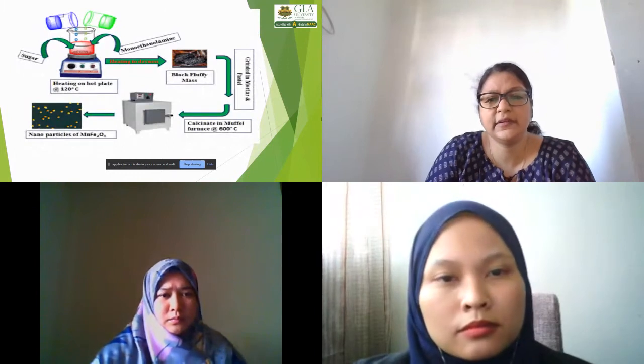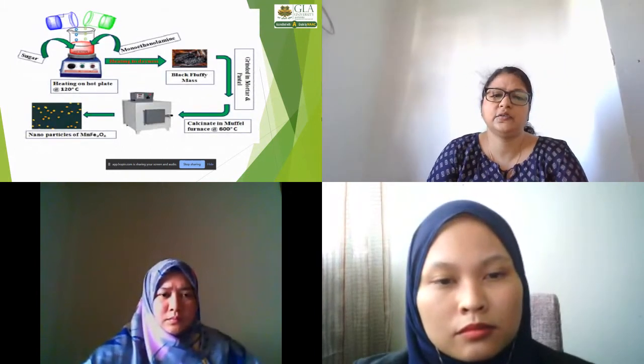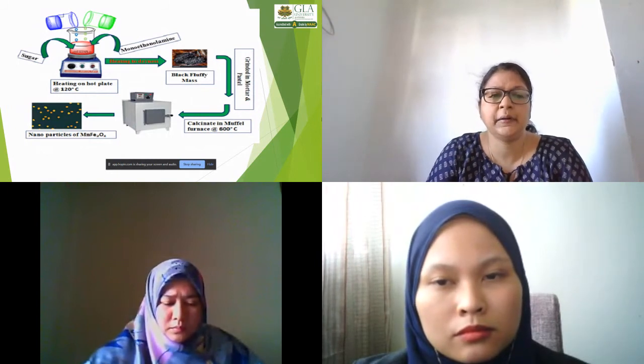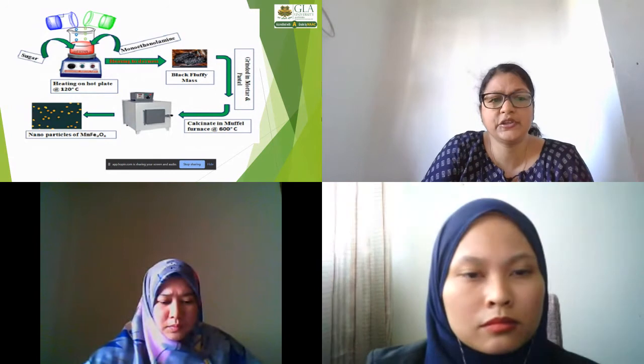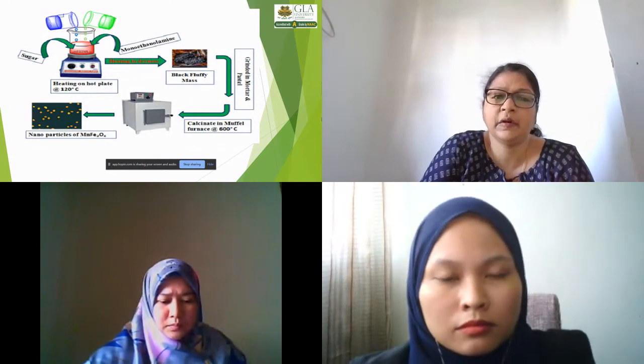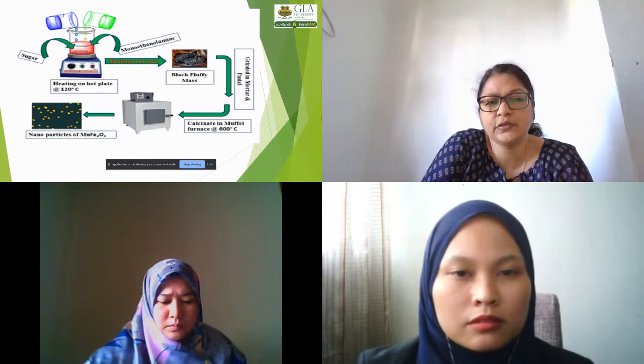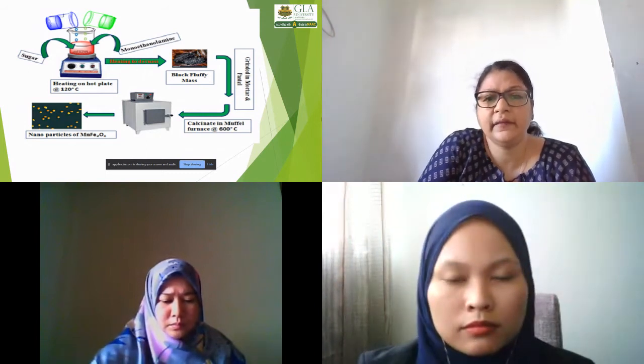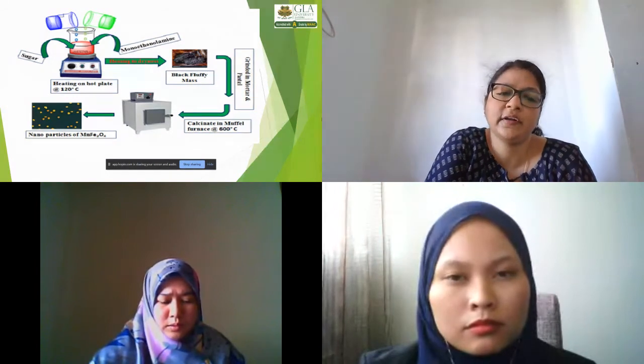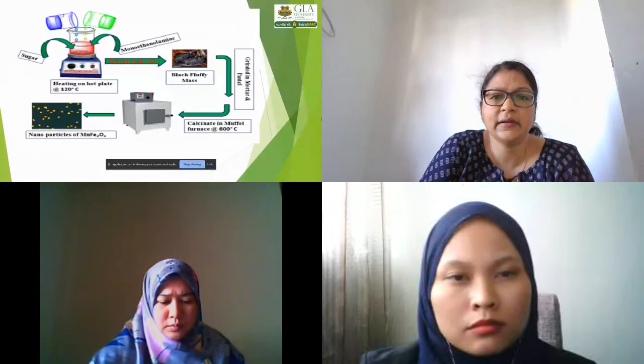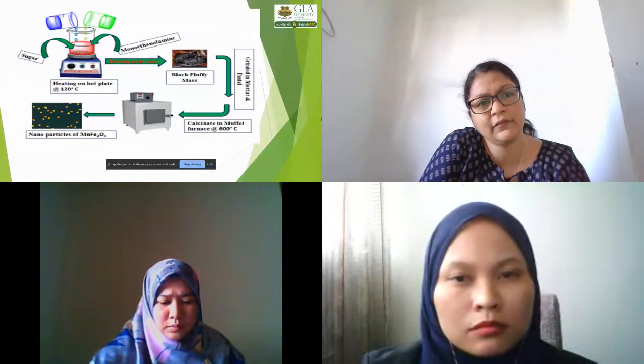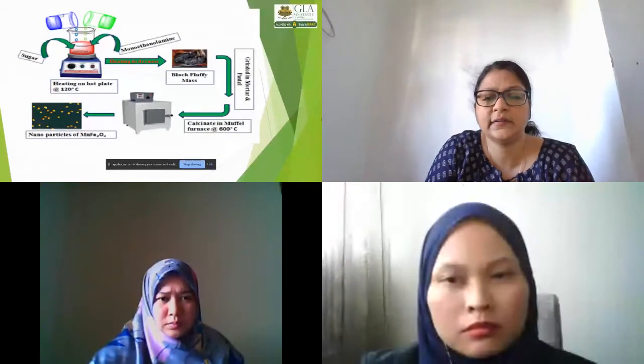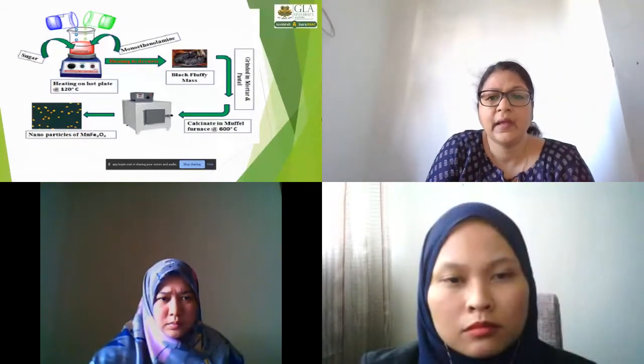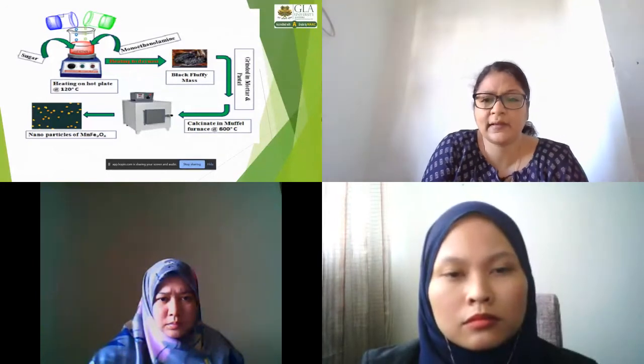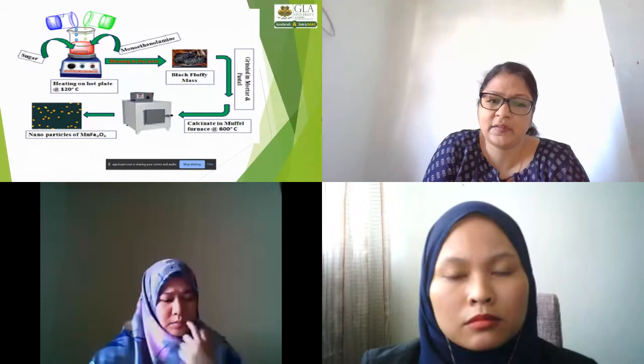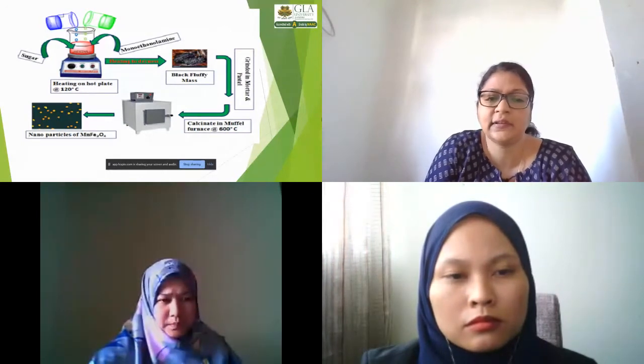This is the process that we use to create the nanoparticles. Basically, we heat vigorously a mixture of the metal oxides in the presence of sugar, nitric acid, and monoethanolamine. The reason for using nitric acid and monoethanolamine is that they create a very explosive kind of reaction mixture, which allows the reaction to get going vigorously, leading to a black fluffy mass at the end, which is then calcined in a muffle furnace, and the end product gives us the nanoparticles.